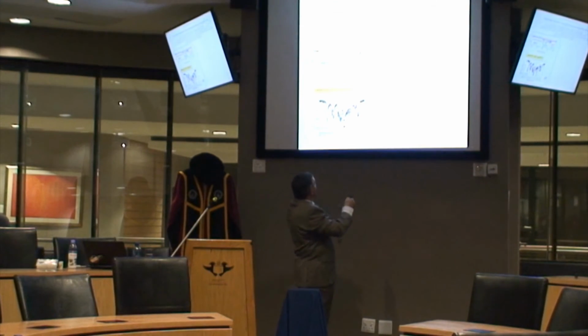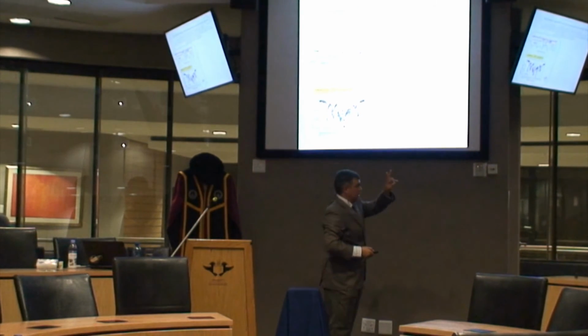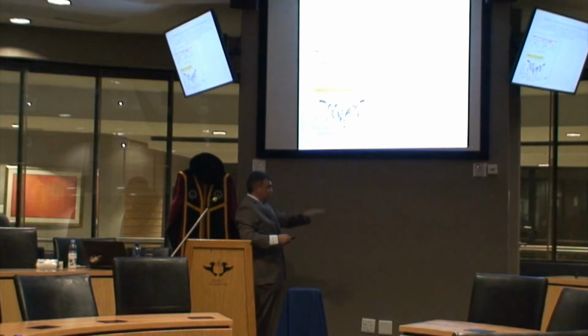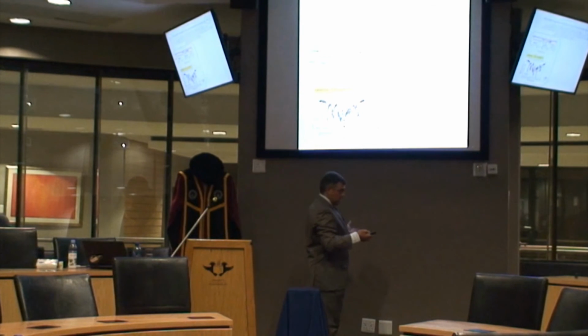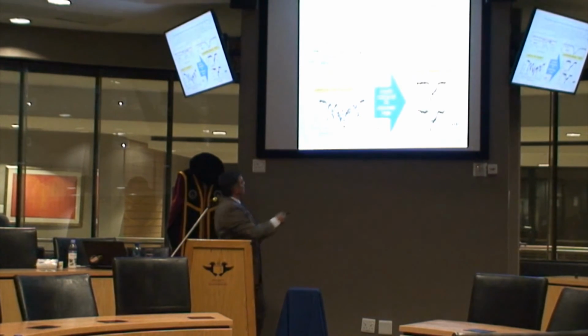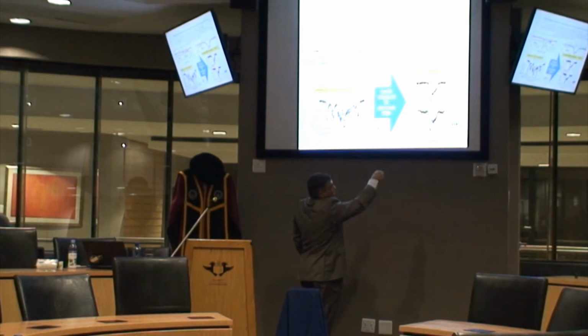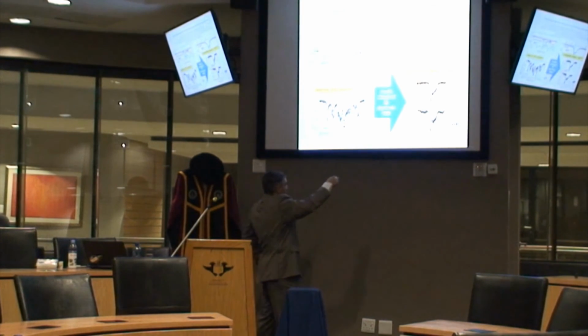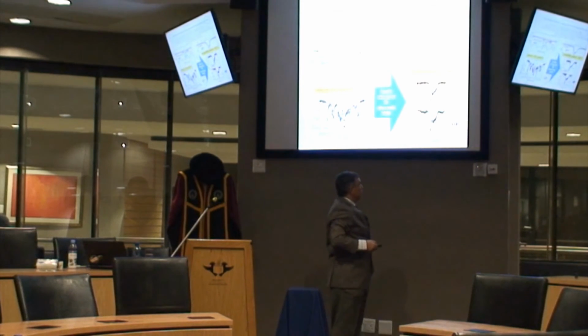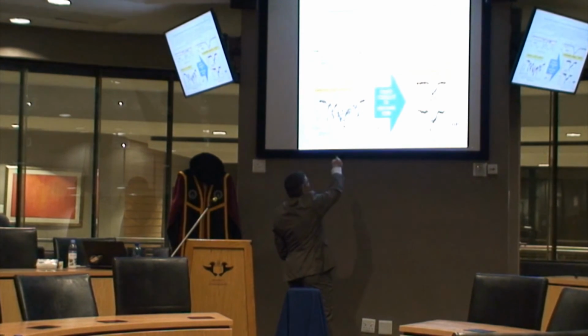And this fingerprint here of the absorption, with all this complicated structure, indicates to us that the iron exists in two chemical states, iron 2 plus and iron 3 plus. And we're able to lower the temperature, and we pick up this complex magnetic signature over here. And the question is, if I now squeeze this material, what happens? Okay? And this is what happens. The spectral profile simplifies. The magnetism changes. We can conclude, and it's a long discussion, that the iron electronic state has changed quite substantially. In fact, you've gone from two chemical states of iron to a single chemical state of iron, which is somewhere in between, if you can understand that.